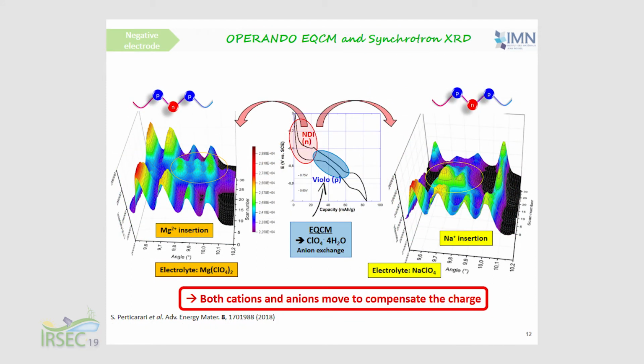We have also done operando EQCM experiments, electrochemical quartz crystal microbalance experiments. And they show that when we have the viologen reactivity, which is of P-type, we see some mass change corresponding to hydrated perchlorate anions. And we have also done operando synchrotron XRD. I will not go into the details, but in the magnesium-based electrolyte, we can see magnesium insertion. In a sodium-based electrolyte, we have sodium insertion. So, to summarize very shortly these operando experiments, we find that during the reactivity of these molecules with both N and P-type units, both cations and anions move to compensate the charge. So this is what we expected.